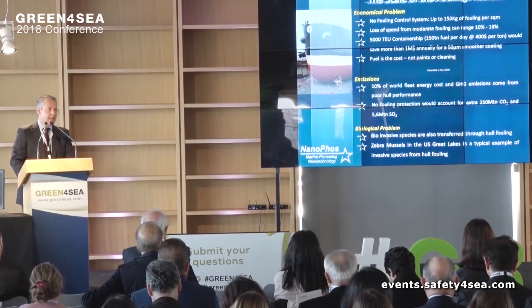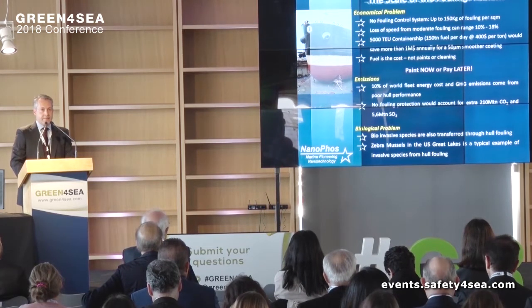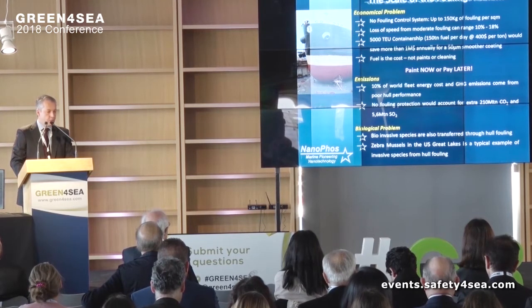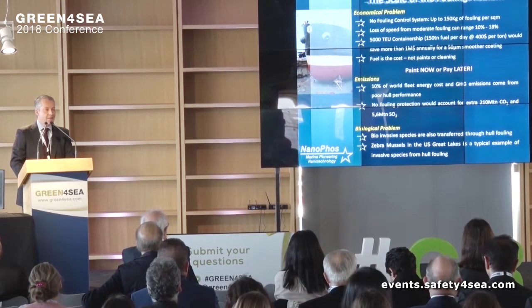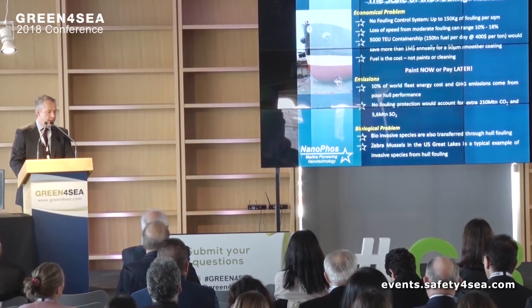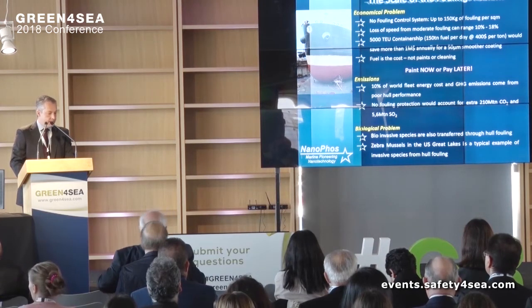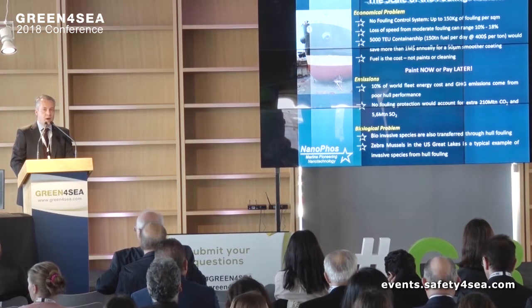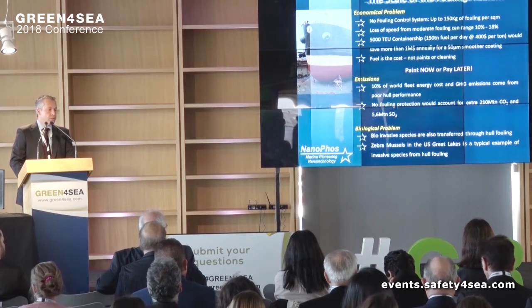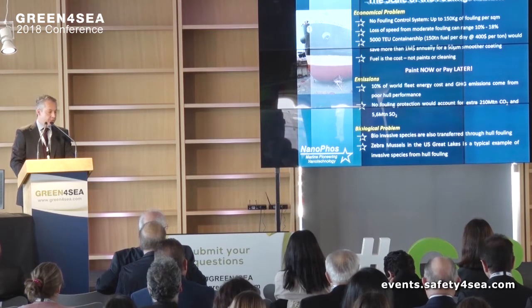Fouling is a huge problem. It has an immense economical effect on the operations per vessel. If there was no antifouling system, then 150 kilos of sea growth would attach on the surface of the hull. The loss of speed from moderate fouling can go up to 10 or 18%, and a medium container ship can save up to $1 million per year just by protecting its hull. In essence, it's pay now, or pay later. So the existence of an antifouling system is essential for the good operation of the vessel.